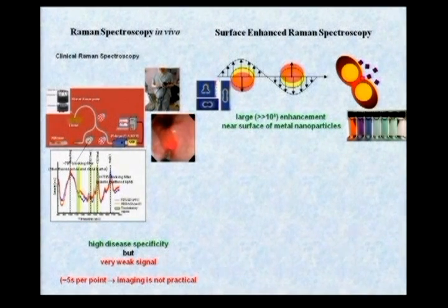Metals have free electrons, the free valence electrons, and so the electromagnetic wave makes the electrons in the nanoparticles oscillate, and if the wavelength of the light is correctly balanced against the size of the nanoparticles, you can get a resonant behavior. It's a bit like pushing a kid on a swing. If you push the kid each time they come back, then the swing gets bigger and bigger and bigger. So you're amplifying the signal. And so the same idea. And so we take metal nanoparticles, such as gold nanoparticles, and coat them with a Raman molecule, and then look at the signal.